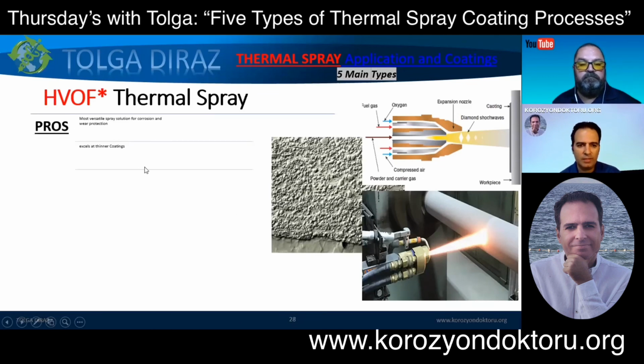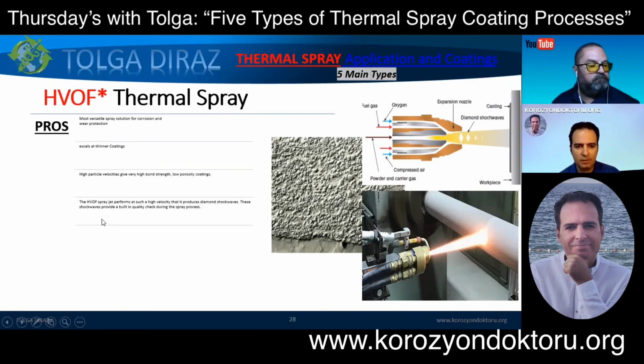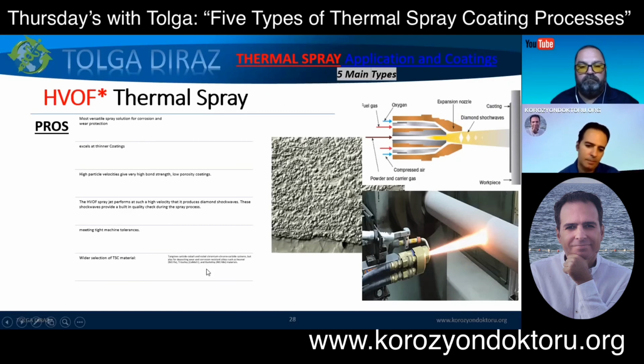So pros: most versatile, excels in thin coatings, high particle velocities, as I mentioned. Such high velocity that it produces diamond shock waves. This diamond shock wave is a quality indicator. If you don't see the diamond shock waves in an application, that means you are not doing it properly. Tight machine tolerances, and a wider selection of material than the flame spray.